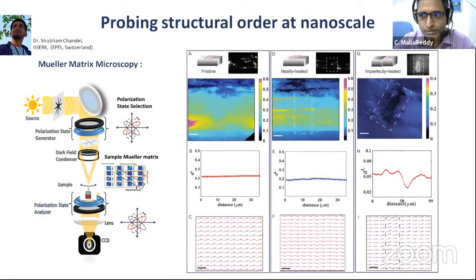Then with my colleague Nirmalya Ghosh, we used the Mueller matrix technique, which is an optical, birefringence technique. It allows you to see the different components of the polarization direction. My colleague built this technique here. He's an expert on this. There are not many people who use this technique at this level. So we found a perfect technique to probe at the nanoscale. The resolution here is about 300 nanometers.